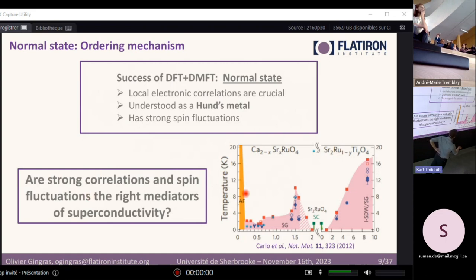And here, I just want to show that it's expected that these spin fluctuations are indeed the mediator of superconductivity in this material, based on simple isoelectronic or non-isoelectronic doping. So what we see here is that by substituting some atoms of strontium ruthenate, you quickly fall into one of these magnetically ordered states here, spin glass or spin density wave. And basically, strontium ruthenate lies in the vicinity of all of these magnetic states. So you can think of it as having a lot of magnetic fluctuations that lead to magnetic order. And once these are suppressed sufficiently, then these spin fluctuations can, instead of leading to magnetic order, lead to superconductivity, and they act as the pairing glue, basically.